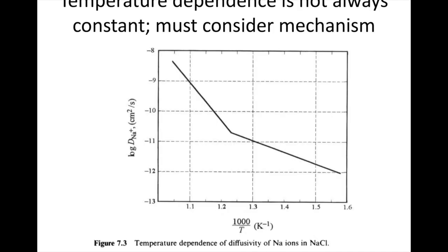So the next thing I want us to look at is something else. I want us to look at this new curve now. So now I just have one of these curves, and I'm looking at the log of diffusivity of sodium ions on the y-axis, so again, a log scale, and I'm looking at 1 over temperature again, and I'm looking at the diffusivity of sodium ions in sodium chloride. So I'm looking at a specific ceramic material and a specific ion. So the reason I want to show you this one is because now the temperature dependence is not constant. So, you know, again, if I try to fit this, it's going to have multiple slopes and therefore multiple activation energies. And so now we have to consider what causes this. We've got to look at the differences in this mechanism because the slope is changing.